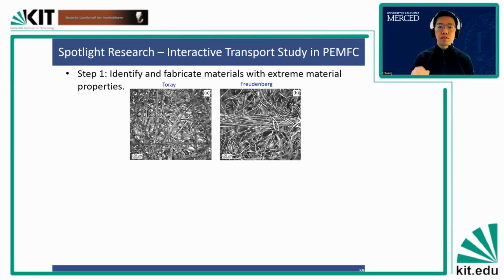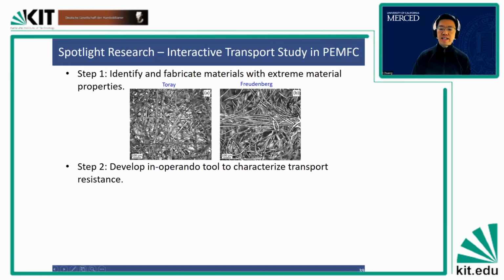In fact, because we want to study extreme properties, we collaborated with companies to make this material when I was at General Motors. We made this material to have very high carbonization temperature. On the right-hand side is the Freudenberg material, manufactured by the dry lay process. There is no resin, just fibers, maybe a little bit of filler, but mostly fibers, mechanically entangled. So both have very different properties and features. We identified them because with these properties, we have a better idea of how to maximize the signal that we study.